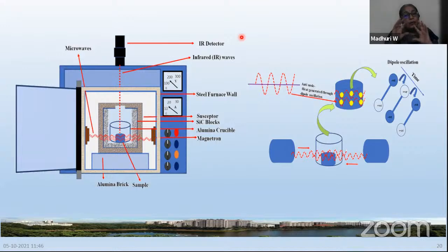If you want to have a better ceramic, you need to keep it at a higher temperature for a certain amount of time so that it is uniformly cooked from all sides, and you get a proper grain structure, grain size, your actual crystal structures, uniformity in the grains. All these things, the densities, you get a higher density here. And there are many more advantages.